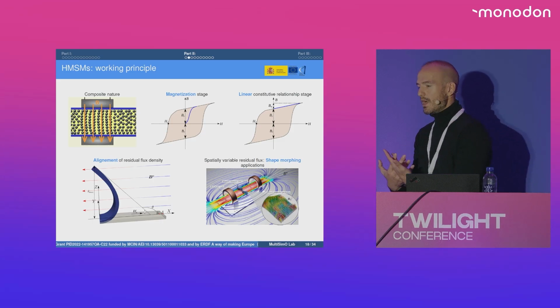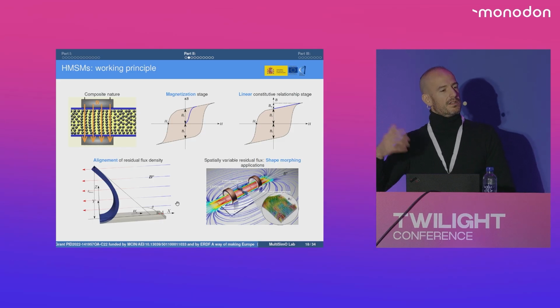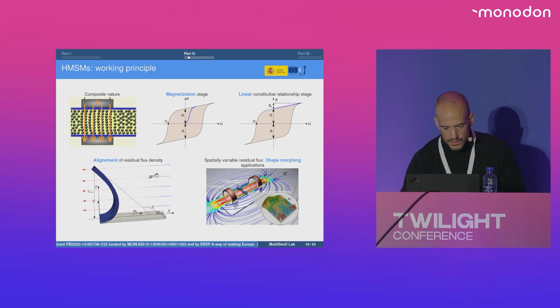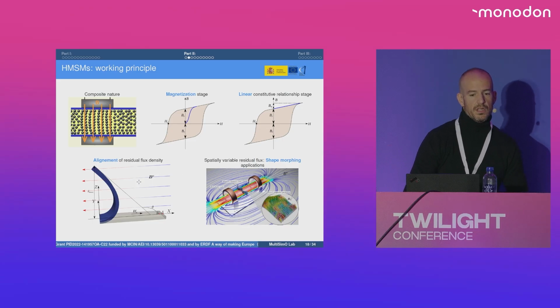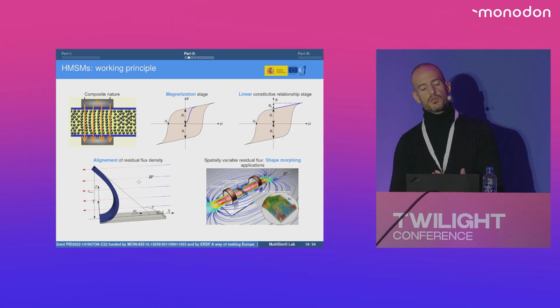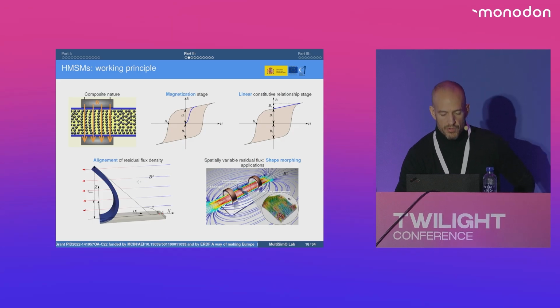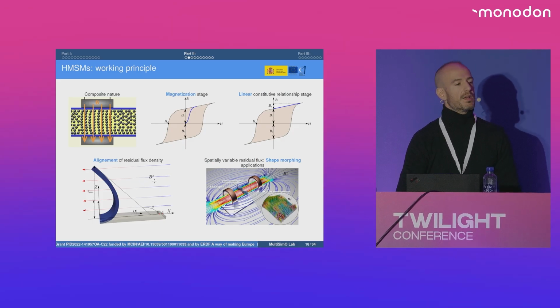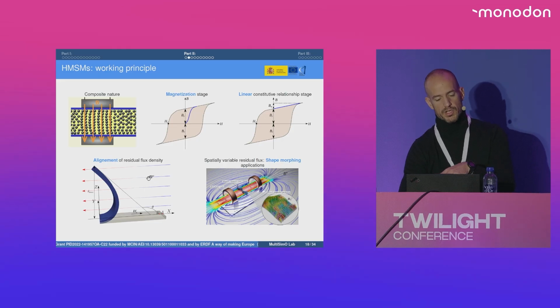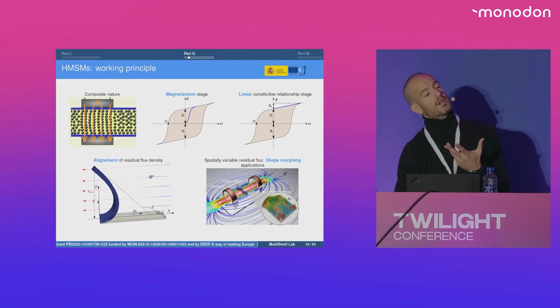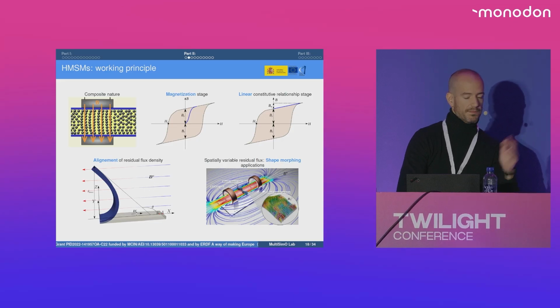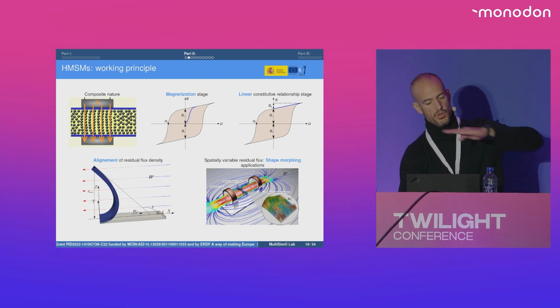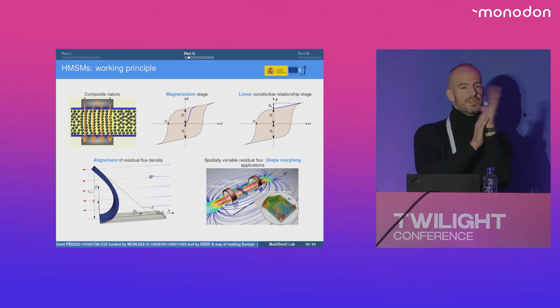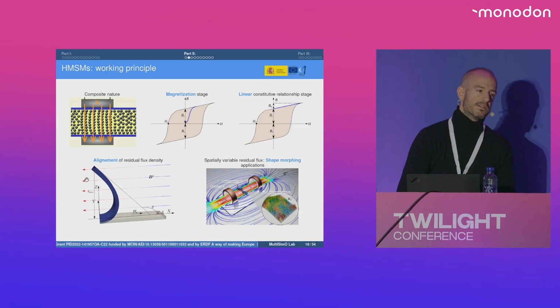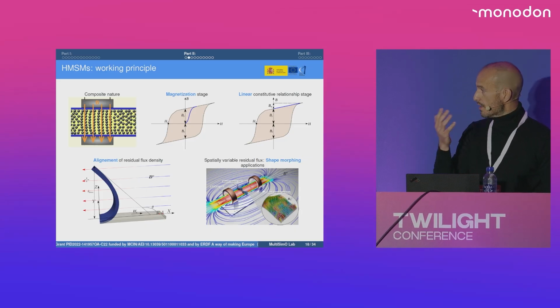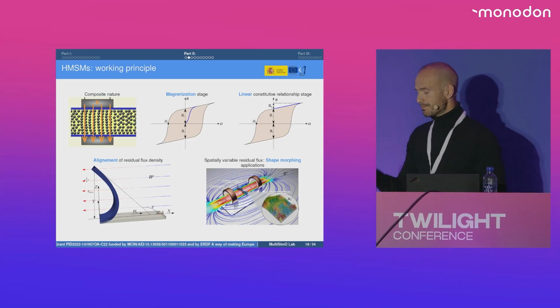But what happens now is that if you come back with a second magnetic field, this one, in the opposite direction, there is going to be an interplay between the remnant magnetization and this second applied magnetic field, so that this one is going to try to align the remnant magnetization with this second magnetic field. So eventually, what it's going to try to do is to move it to this side, to the left side, and then you're going to have this bending type deformation. Okay? So these are magnetically induced deformations on the solid.